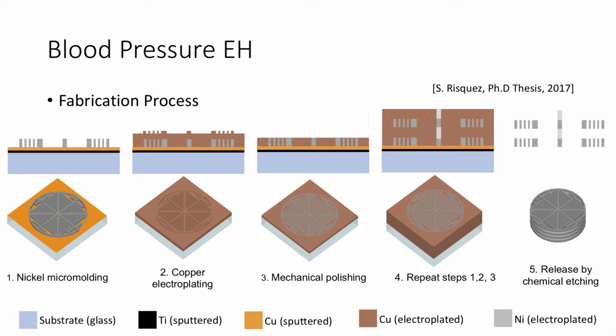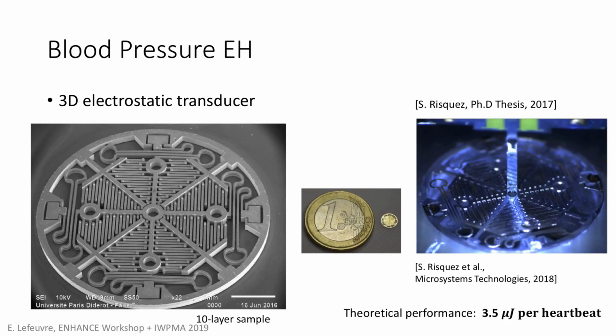And the most important point is that it takes a very long time to get one layer. To get one layer? One layer. So if we do it in our clean room, not an industrial process, to get one full layer perfectly done, it's more than 3 days. Just for one layer. That's a photograph of the 10-layer sample.